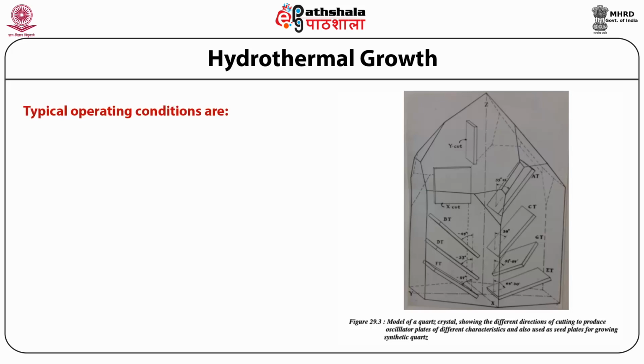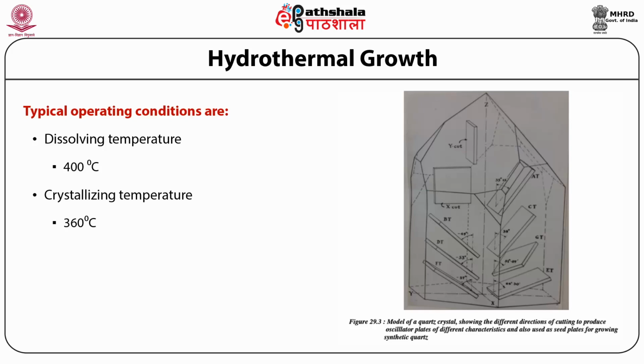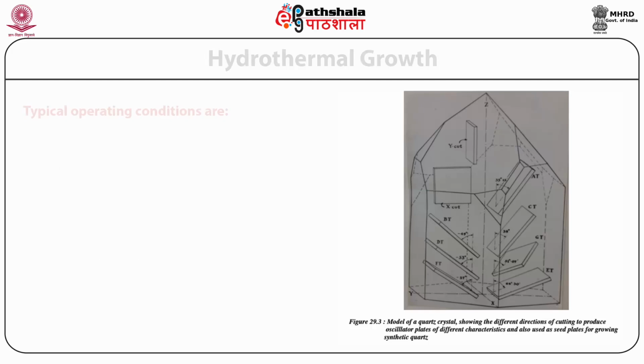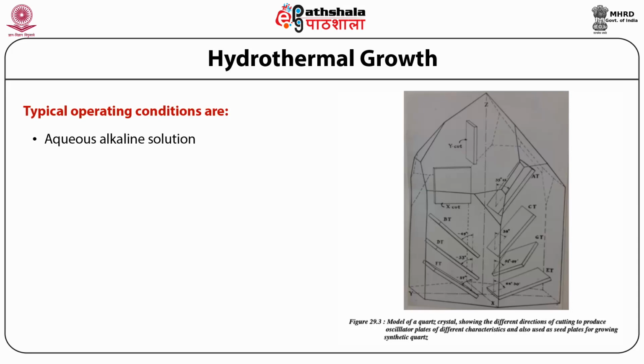Typical operating conditions for the growth of quartz are dissolving temperature 400 degrees centigrade, crystallizing temperature 360 degrees centigrade. Temperature difference delta T is maintained at 40 degrees centigrade. The degree of fill is around 80%. Aqueous alkaline solution, 1 M of sodium carbonate or sodium hydroxide.